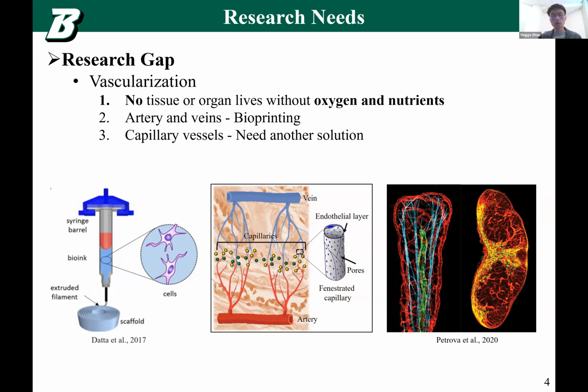But for the capillaries, which are from 1 to 10 microns, it's really hard given the current bioprinter resolution, especially the material limitation. Usually we use hydrogel to print the scaffolds, so you can imagine it's really hard to create 1 to 10 micron tubes or channels within the hydrogel scaffolds just by using bioprinting. Also, there are some surface pores on the capillaries in our human body, which means the surface pores will be in nano size, not micro size. So it's even harder for the bioprinter to create the surface pores.